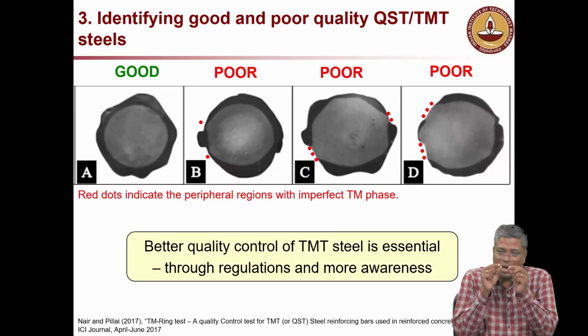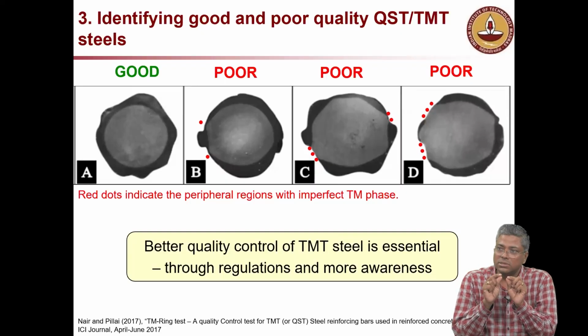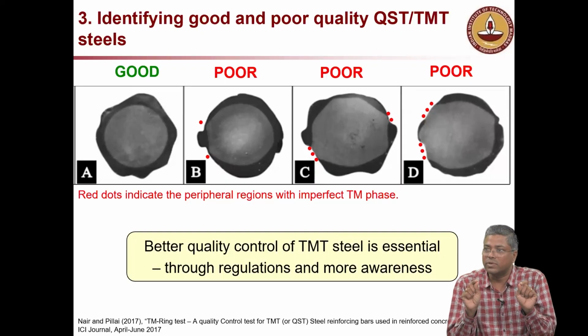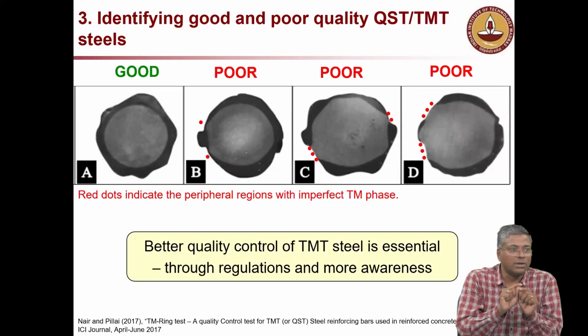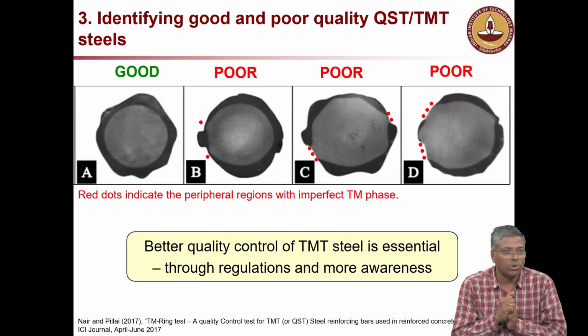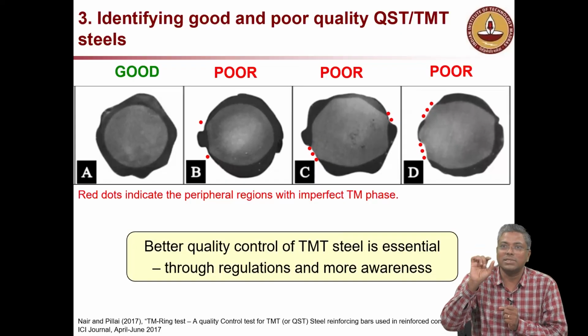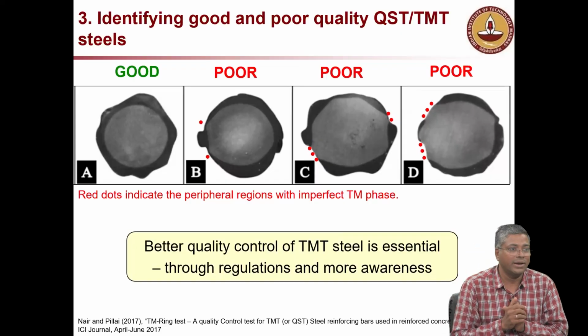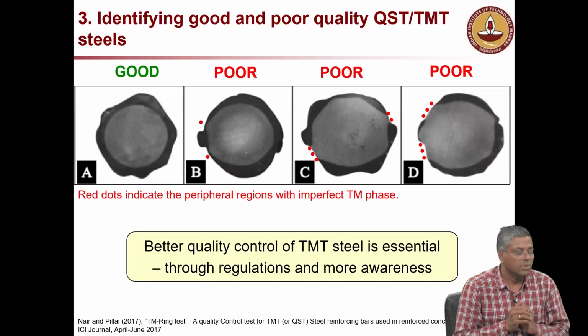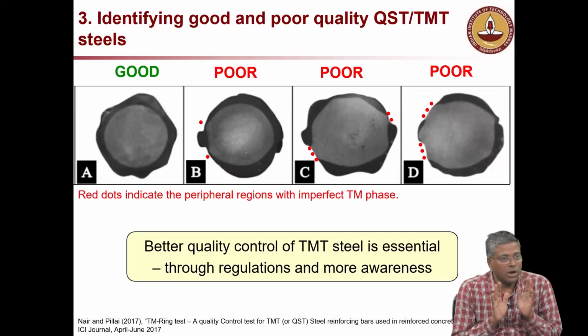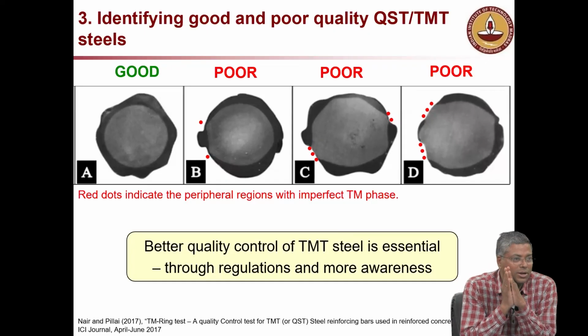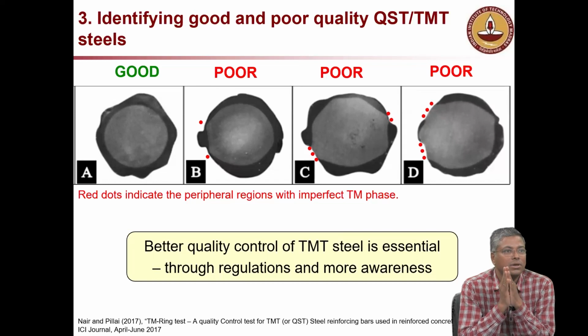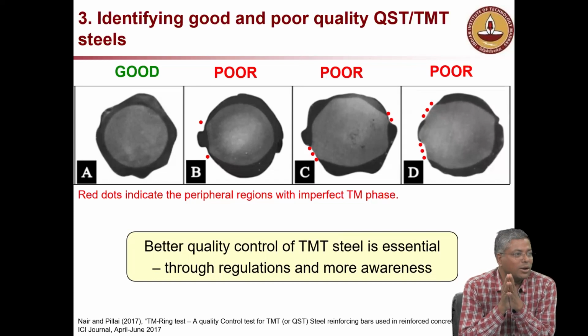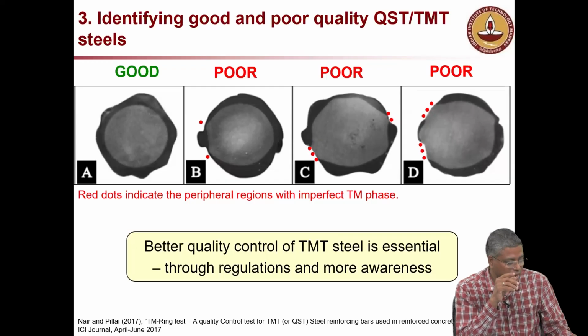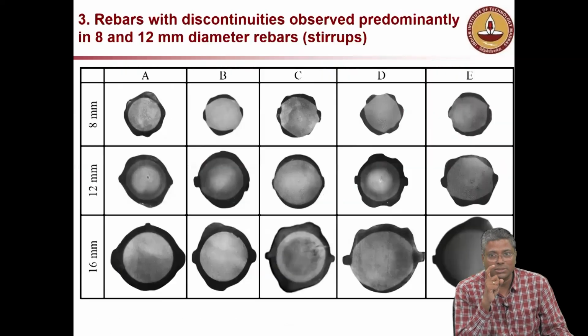Why? Because you have two dissimilar metal surfaces in contact with the cement or concrete, so you can have a corrosion cell. Small micro cells can form where you see the red dots. This is probably one of the reasons why our structures built with TMT bars are corroding, and they corrode where the bend is. I'll show you that also.